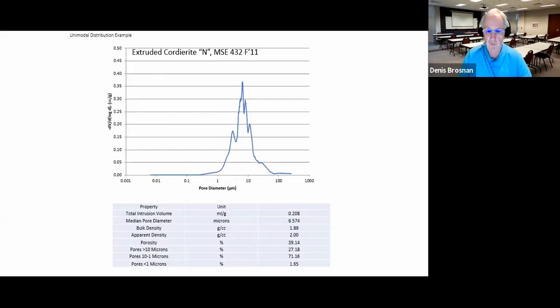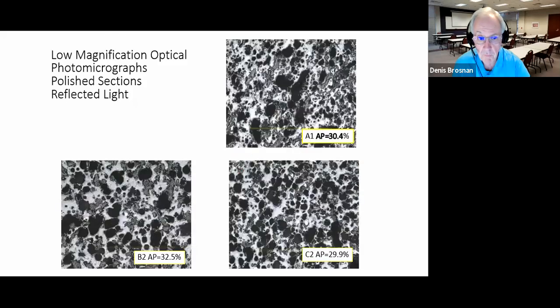We had a pore size distribution. The peak in pore sizes here was in the area of 1 to 10 to 20 microns or thereabouts, about as big as some of the kaolin crystals, kaolin particles that were present. So that was, I have to correct this. This is not cordierite that we made. This is cordierite that was commercially made. So pretty much a unimodal pore size distribution in commercial cordierite.